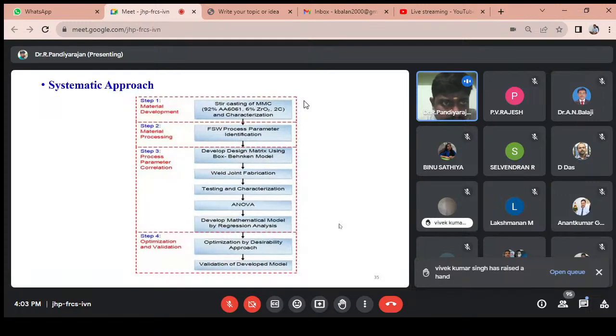This is the systematic approach followed to find the optimum solution of friction stir welded aluminum based composite material. Step number 1 is material development. Material development means we have to fabricate the composite material and prefer a work holding device for 100 mm length, 50 mm width and 6 mm thickness. Material preparation is done using a wire cut EDM machine. This is the material development process, step number 1.